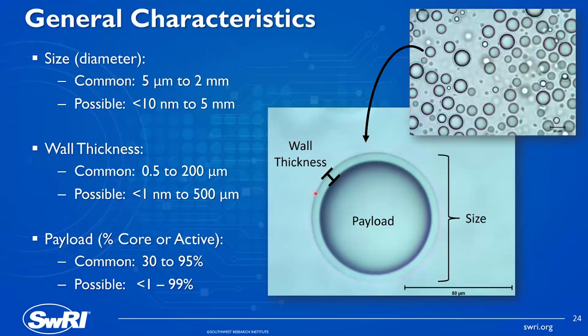Wall thickness, this really more applies to your core shell microcapsule. So as the name implies, the thickness of that wall. Roughly a few hundred nanometers is going to be the low end, especially with some of your emulsion-based processes, your in situ polymerization, interfacial polymerization, up to hundreds of microns. As you start to go higher in the thickness of shell, you lose payload, and so it becomes less economically feasible. But you can certainly go higher than 200 microns. It's the low end that can be problematic. Possible, you can have a monoatomic layer. So think about a micelle, just a simple layer of amphiphilic molecules surrounding a droplet inside of maybe an aqueous phase, up to hundreds of microns, maybe even millimeters if you want a really tiny core.